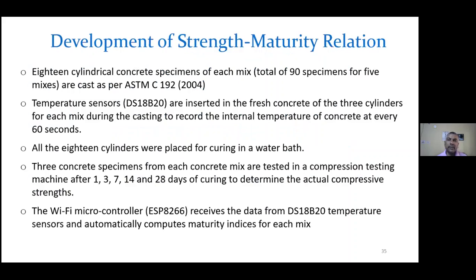Now the next thing is development of the strength maturity relation. 18 cylindrical concrete specimens of each mix. Once we know the datum temperature, we prepare cylindrical specimens, 18 of each mix, a total of 90 specimens for 5 mixes, cast as per this code. Temperature sensors are inserted in the fresh concrete of 3 cylinders for each mix during casting to record the internal temperature of the concrete every 60 seconds. All 18 cylinders are placed for curing in a water bath.